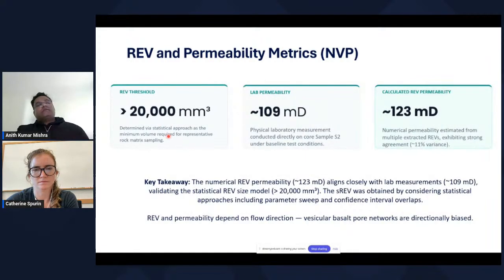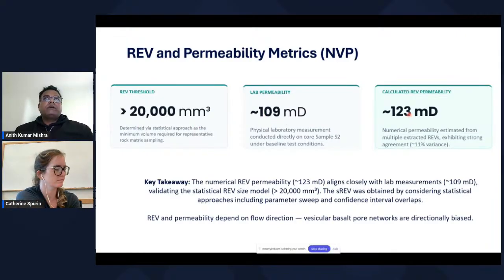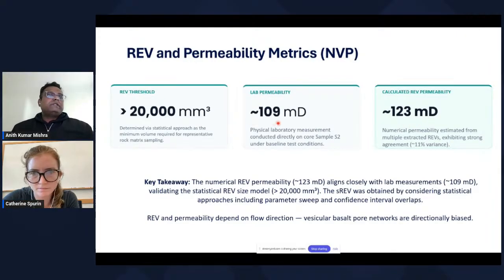So from that study from the Newer Volcanic Province, what we actually established is that more than 20,000 cubic millimeter voxel size, sample size, is required to get a representative elementary volume where we can have some sort of confidence. And this is validated by a lab-based permeability and the numerically simulated permeability done on the REV samples. On the REV samples, the numerical permeability resulted in a value of about 123 millidarcy. And using the same sample in the lab, using the standard core flooding experiments, we found a lab-based permeability of 109.